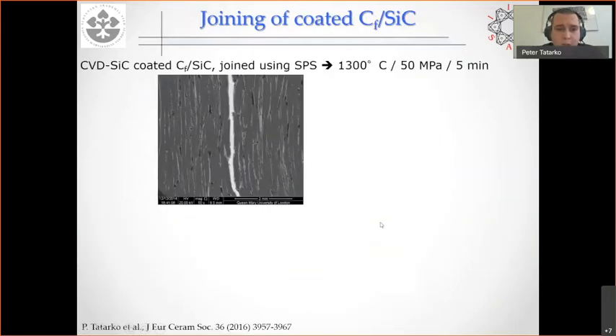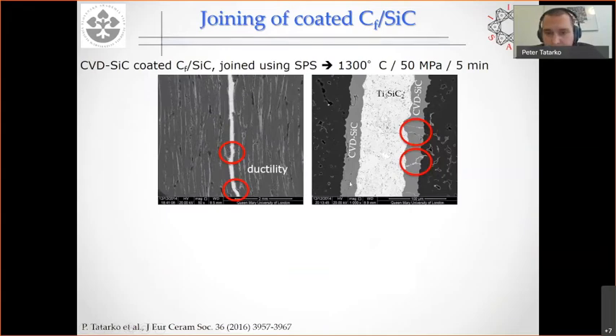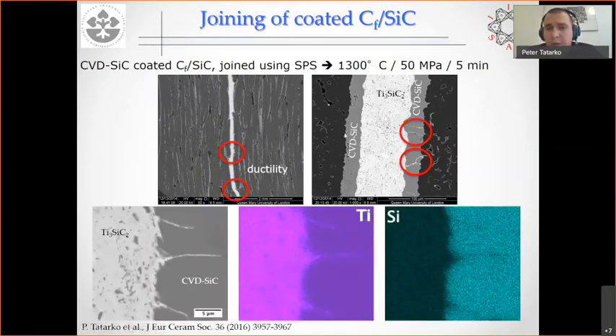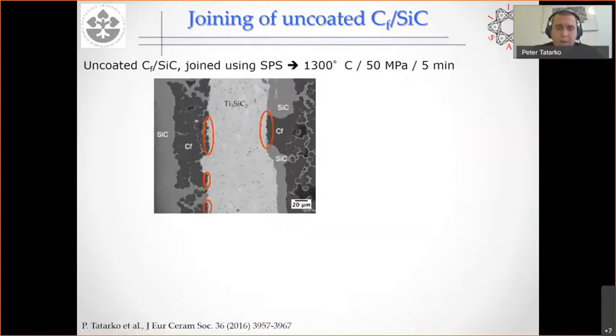So coming to the results, here is the cross section for the coated sample. The first thing we noticed was that the foil, the interlayer, was really ductile, because you can see it conformed very well to the rough surface of the CMC. Another important thing: here you see the CVD silicon carbide coating, and this coating always has some cracks because of the thermal mismatch between the coating and the matrix. In our case, after joining, we actually filled up these cracks with our filler, in other words, we healed these cracks. You can see here the EDX mapping: it is depleted in silicon but enriched in titanium. So it's clearly seen that it's our joining filler that came in and healed the crack. This showed in the end a very good result for strength and for mechanical performance.